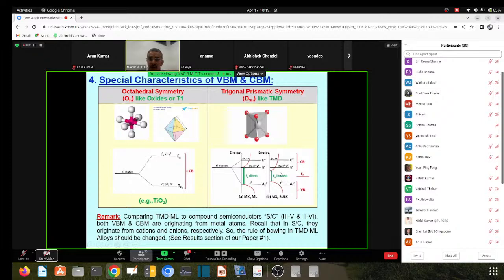A special characteristic about the valence band maximum and conduction band minimum is very important, because in this kind of material the band edges are dominated by the metallic states. It's not like compound semiconductors, like III-V or II-VI, where the valence band is known to originate from anions and the conduction band from cations. Here it's purely from metals, both of them. So why is that so? Because I will show some group theoretical splitting of these states under different symmetries.